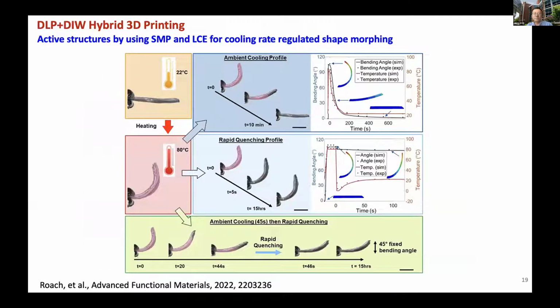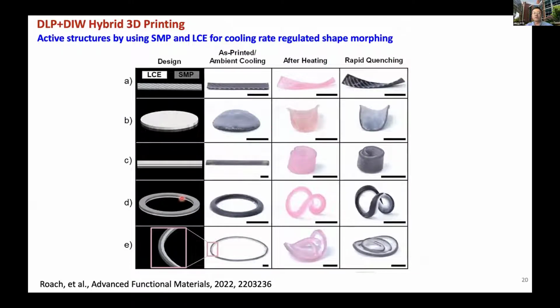For example, we can ambient cool it, which is normally slow, like I said before. I can cool it down for maybe 44 seconds until I reach this shape. Or I can quench it, then the material will be locked into this shape. So you get lots of flexibility. And at this shape, because you have shape memory polymer, the material is actually very stiff. So we can achieve many different structures, utilizing the flexibility offered by the 3D or 4D printing. We can control how we lay the LCE fibers. We can achieve this kind of helical shape, or this kind of saddle shape, or make a coil. Many different shapes.